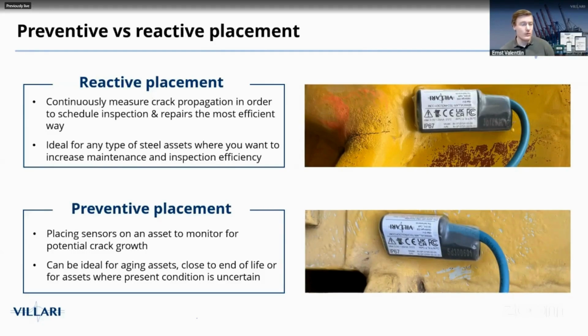On the other side, we see also a lot of preventive use of the sensors. In these cases, the system is applied in locations where there are no cracks present in the steel yet. Rather, the sensors are placed in places where the cracks are expected to start occurring, to be able to flag it early if it does occur. In those cases, we also see a distinction in how it is determined where the sensors will be placed. In some cases, that is done based on calculations. So people, for example, have a bridge or a crane, and they have the FEM calculations to figure out which exact areas of the crane are most sensitive to accumulating fatigue stress and growing fatigue cracks towards the end of life. In that case, the calculations are done, and based on that, a plan is made of where to apply the sensors.